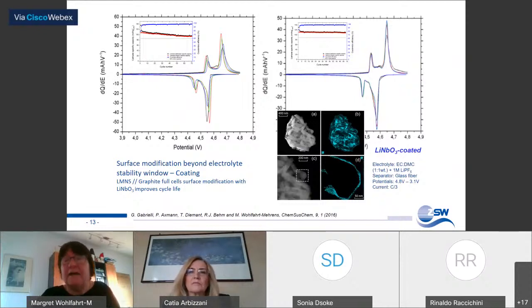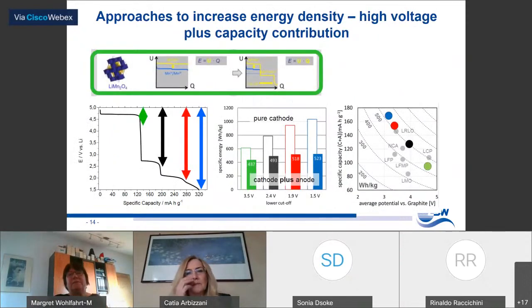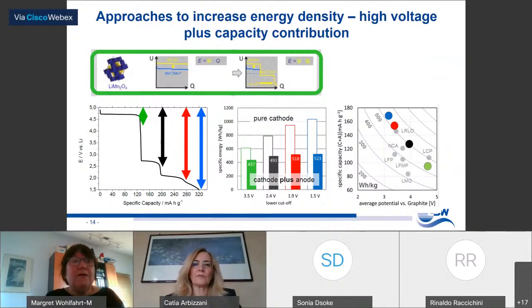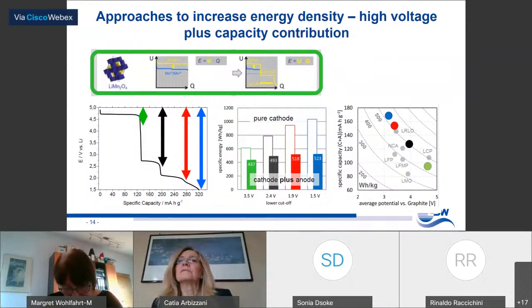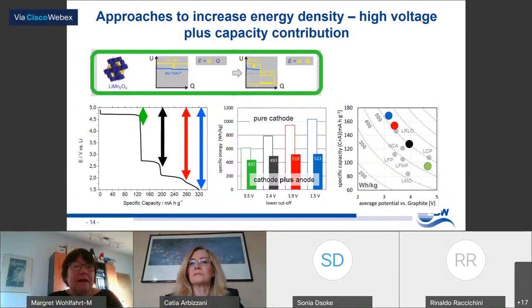By surface modification of the spinel with lithium niobate coating, and we are now working on other surface modification. For lithium niobate is also not the most sustainable and cheapest material. So in order to increase further on the energy density, this is to use the high voltage plateau and the additional capacity of the lithium nickel manganese spinel.